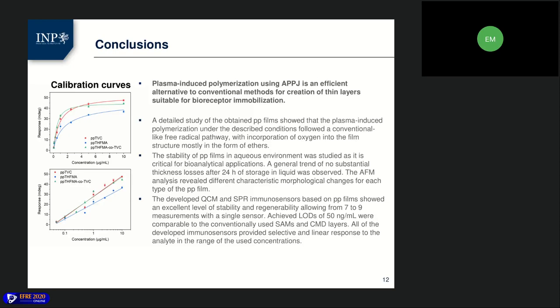A detailed study of the obtained plasma polymer films showed that plasma-induced polymerization under the described conditions followed a conventional-like free radical pathway with incorporation of oxygen into the film structure, mostly in the form of ethers. The stability of the plasma polymer films in aqueous environment was studied as it is critical for bioanalytical application, and the general trend of no substantial thickness losses after 24 hours of storage in liquid was observed.